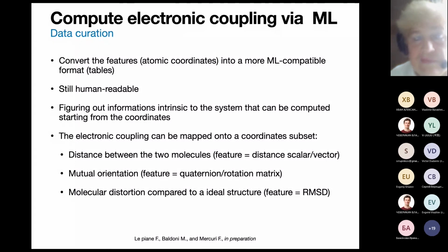So we want to convert the features, the atomic coordinates, into a more machine learning compatible format. It has to be, unfortunately, still human readable because we need to modify it by hand from time to time. So we need to figure out what kind of intrinsic information of the system can be computed starting from the coordinates and injected into the machine learning algorithm. The electronic coupling can be mapped onto a subset of the coordinates. From the previous results, we understood that the distance between the two molecules is the main feature, and also the mutual orientation, but also the distortion of each molecule inside the aggregate compared to an ideal structure. It can influence quite importantly the value of the electronic coupling.